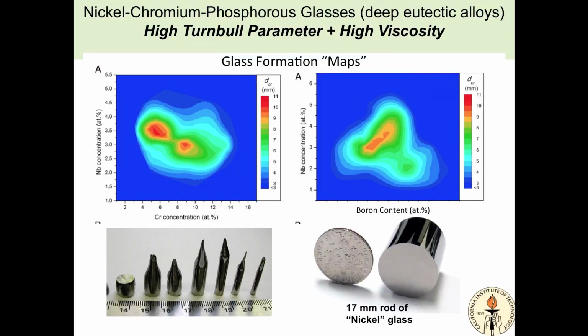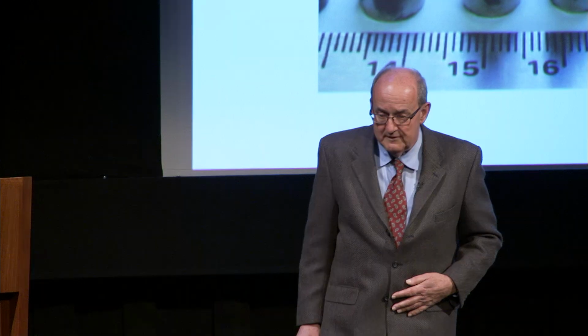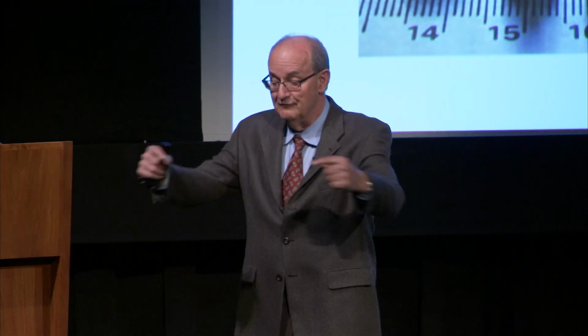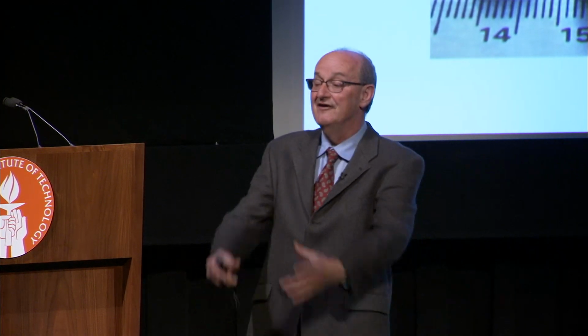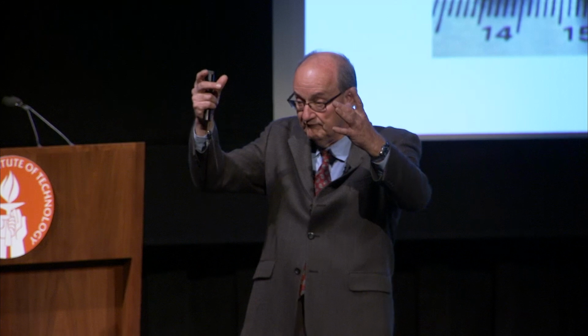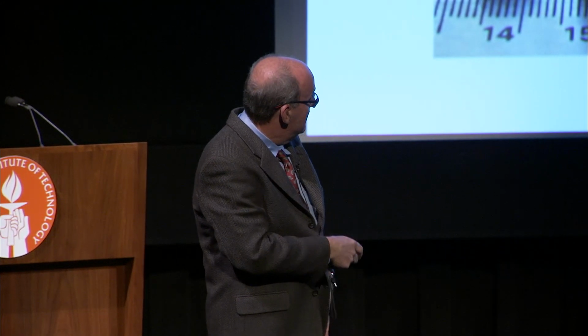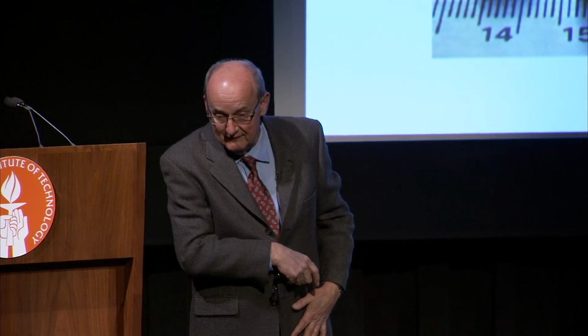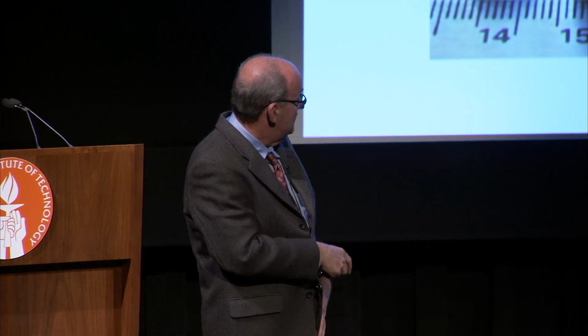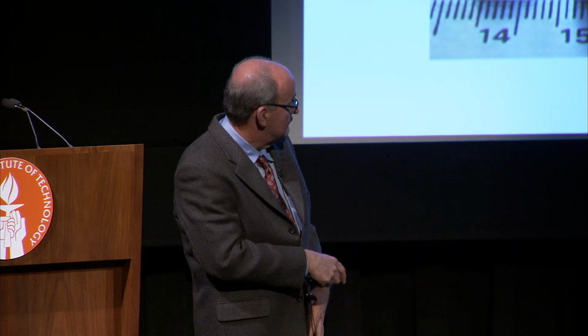This is how we quench little samples of metal in a tube, and as we get closer and tune it up, notice the chromium content here, that's niobium, that's boron. Notice these have a lot of detail. Why do they have so much detail? Because the eutectic point is one point in the phase diagram, and when you hit that point, the glass forming ability goes through the roof. So you tune it up and find the peaks. You find the eutectics, and there's a nickel, chromium, phosphorus, boron glass.